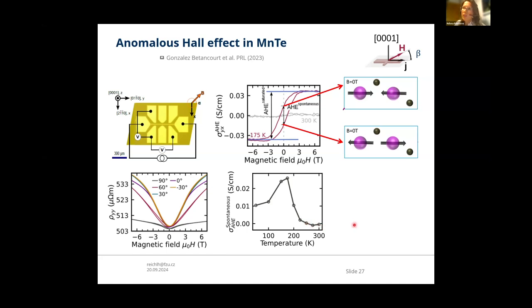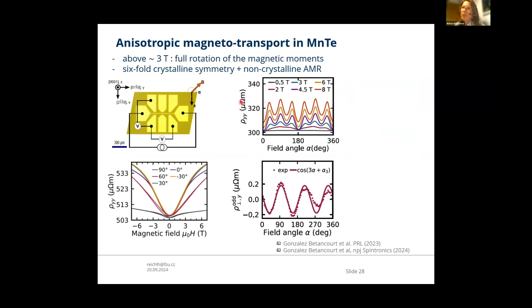So this is the anomalous Hall effect, and I mentioned also that the longitudinal data contain some interesting information, and this is about the anisotropic magnetoresistance, which we knew very well contains a non-crystalline contribution, which has this cosine square symmetry. However, there is also a crystalline contribution, which has the six-fold symmetry. This is what we can nicely see here, which indeed copies the crystalline properties. In the conventional picture, if we thought about some ferromagnet, this kind of crystalline contribution we would not expect in the transversal signal,